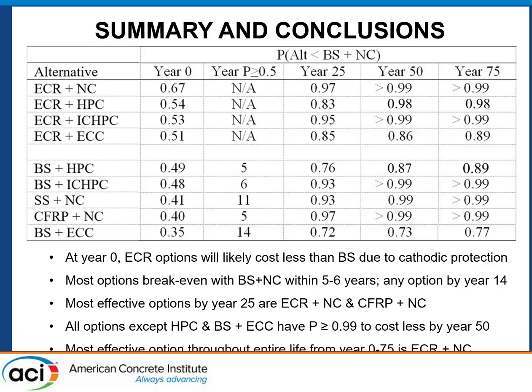Now, kind of to summarize some of the information on that table, first, we have in the very first column at year 0, it shows some of these probabilities that the alternative, shown in the very left column, will cost less than the baseline. So all of the upper 4 options there, ECR, the epoxy-coated rebar, all of those, as can be seen, have a likelihood of costing less during the initial construction than the unprotected steel and normal concrete. Even the ones that are more expensive initially, shown on the lower 5 there, all of them appear to not be too far away from 50%.